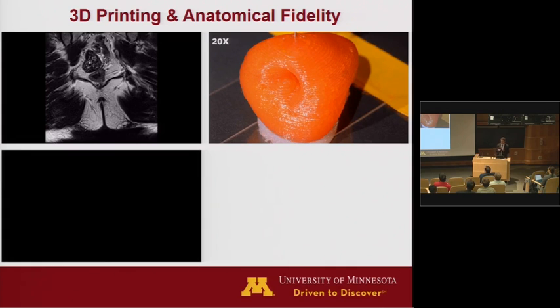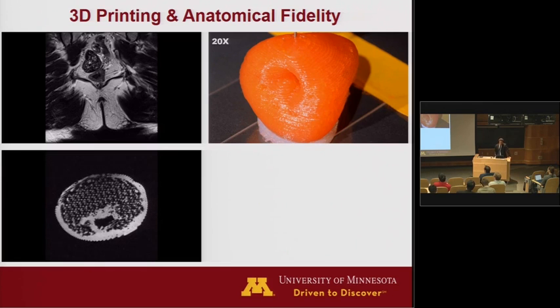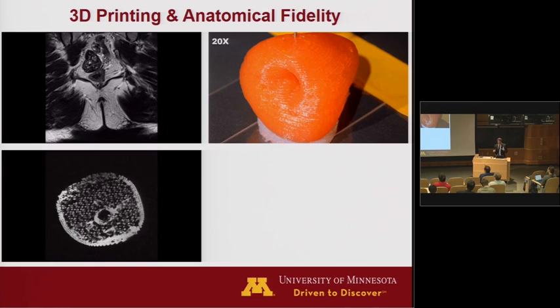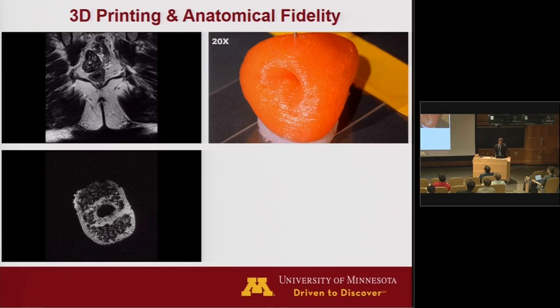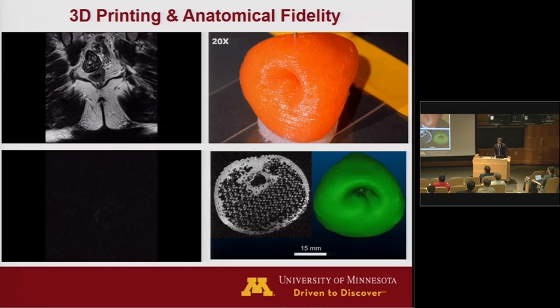Now what we can do is we can take this organ model that we've printed and then do an MRI scan on the organ model itself. So this is actually an MRI scan on the organ model. And then that way we have a digital representation of both the original organ and of the organ model. And we did do some software calculations, some comparison tools to figure out exactly the anatomical fidelity between the organ model and the original organ. And these are surface calculations. They're not full point calculations, but they're surface calculations. But the overall anatomic fidelity using these 3D registration techniques was found to be about 98%, which is pretty accurate.